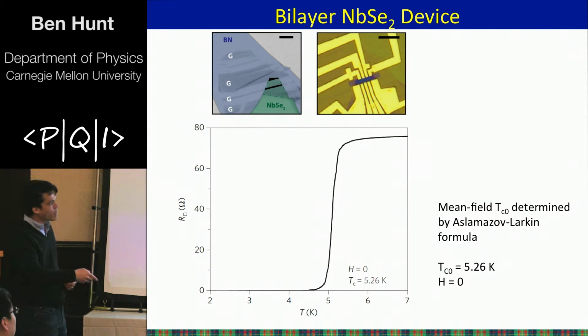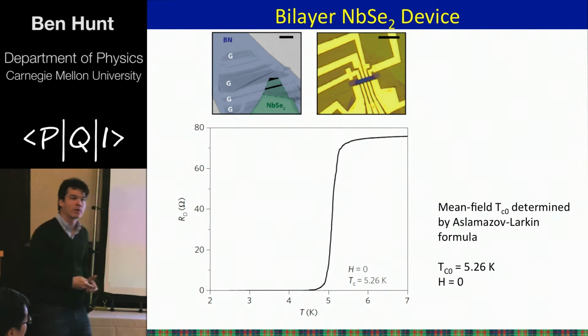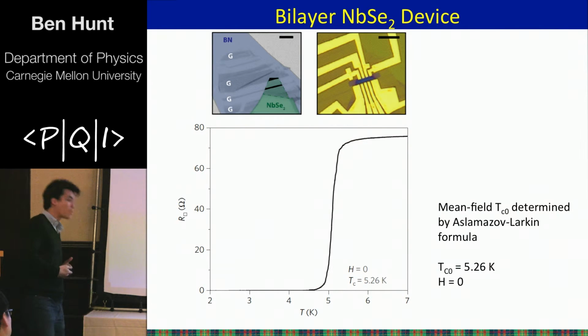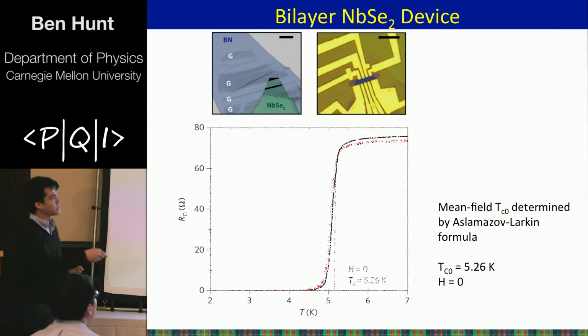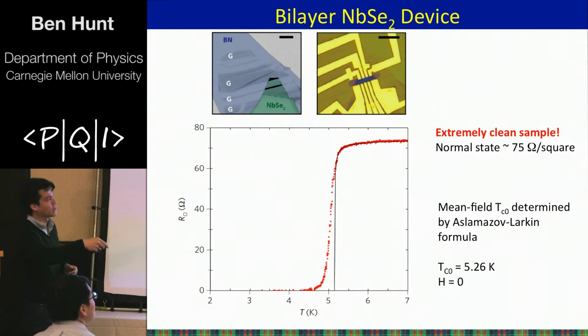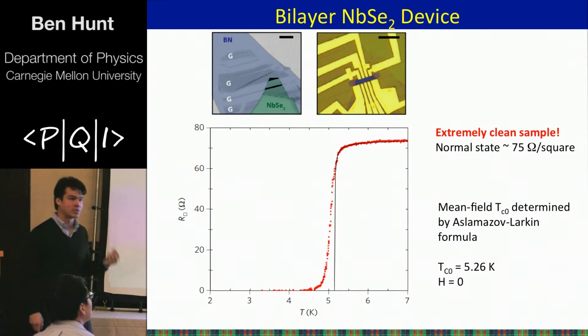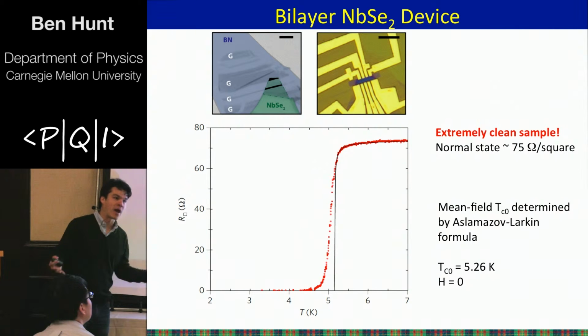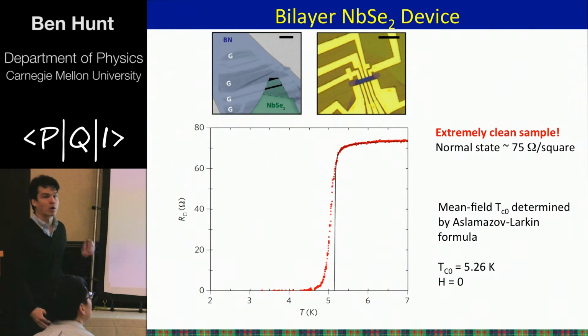And the important thing to note about this compared to the disordered samples previously is that this sample is extremely clean. It's crystalline, right? It's a single crystal of niobium diselenide. It has only about 75 ohms per square resistance in the normal state. And so we're really in the clean limit of a superconductor where the mean free path is much longer, well, somewhat longer than the coherence length, okay?